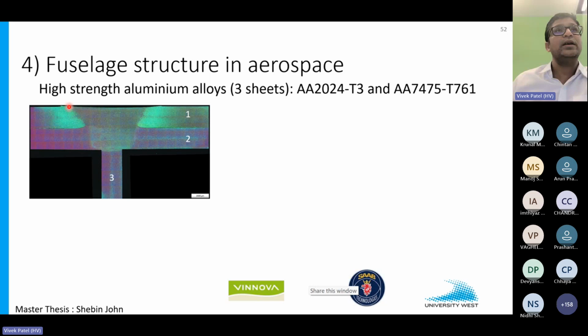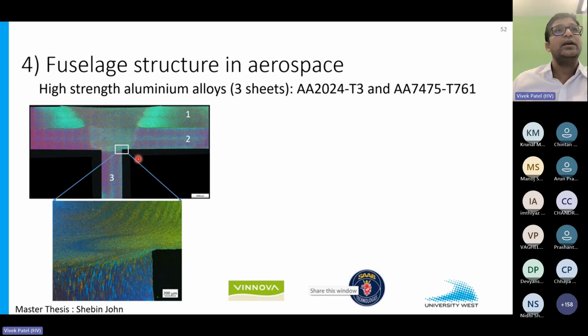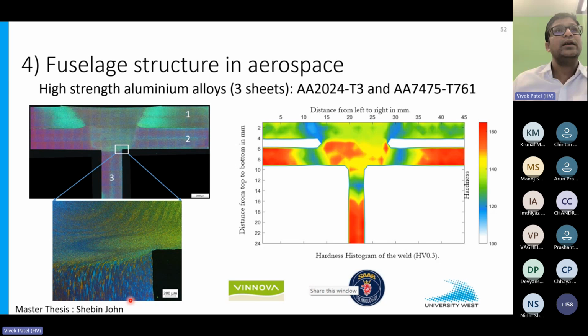And after process optimization, you see this complete full penetration in this wall also. And we welded 2024 and 7475 in three sheets together in one welding pass. And see how close the interface looks. There is a significant refinement you can see in the weld nugget compared to the parent material. And we also tried to map the hardness, and we know that the 2000 and 7000s are quite high strength alloys, so they possess higher hardness and higher tensile strength compared to other aluminum alloys. So it's important to see where the hardness drop is coming. We found that the weld nugget does not have too much reduction in hardness compared to the hardness of the parent material after these T3 and T76 heat treatment conditions. And as a next task, we are going to investigate this for fatigue strength.